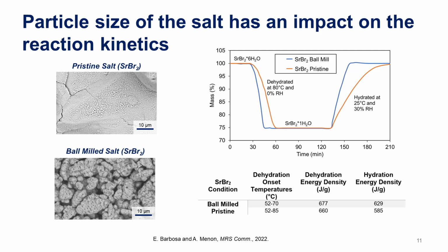what we notice when we do thermogravimetric analysis is the ball milled salt, shown here in the blue curve, ends up dehydrating much quicker than the pristine salt. More importantly, when we try to hydrate it, you can see that the hydration reaction is much quicker when we work with the ball milled salt rather than the pristine salt. And so the particle size has a significant impact on the kinetics of these reactions.